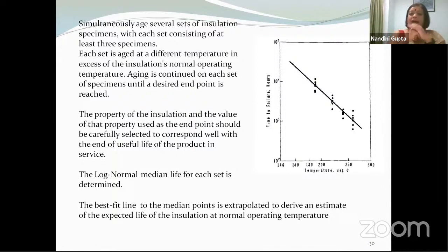Let's say you're performing at 250. When you expect to operate at 150, you have to make sure that all the chemical processes and the physical processes that happen at 250 are the ones that happen at 150. Say, for example, you have a material which melts at 250. You will not even be able to test, and it will make no sense to test at 250. Maybe it's a material which undergoes certain chemical process. Maybe it's a material which has certain chemicals which will react beyond 220. But you are expecting to use it at 120. There is no point in operating at 220.